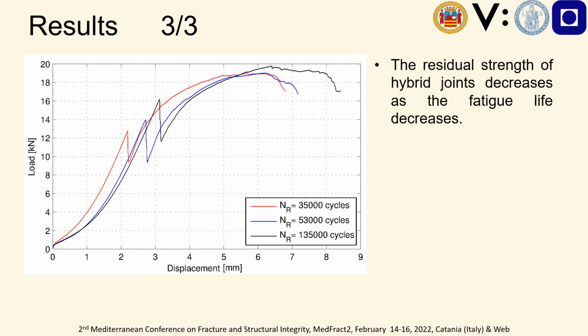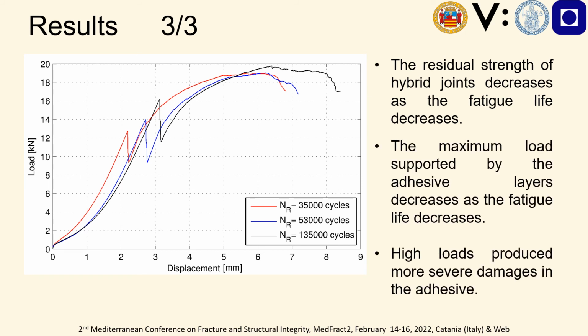Herein you can find the results related to the assessment of the residual strength of hybrid joint. And in particular, we can observe how the residual strength of hybrid joint decreases as the fatigue life decreases. Moreover, we can observe how the maximum load supported by the adhesive layer decreases as the fatigue life decreases. And in particular, higher load produces more severe cracks.